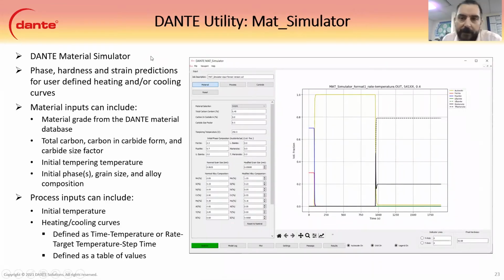So then we have a mat simulator. So MatSim, like I said, is phase hardness and strain predictions for heating and cooling curves that we define. So thermocouple data and stuff. Material inputs are, again, same material inputs. I've been beating on you guys, I'm sorry. So we use DANTE grade, material grade, use carbon and carbides. It has carbide dissolution and separation models built in here. And this is for a 1D analysis. So this is just time temperature data for that point in space. Process inputs include the initial temperature, and then heating and cooling thermocouple data and stuff that you can input as the process tab.